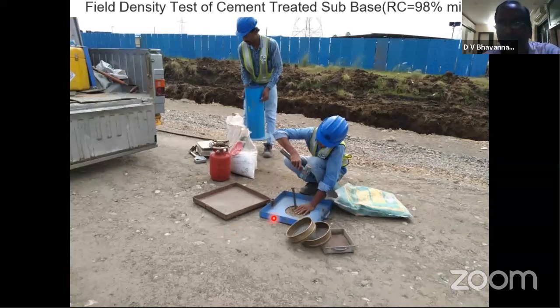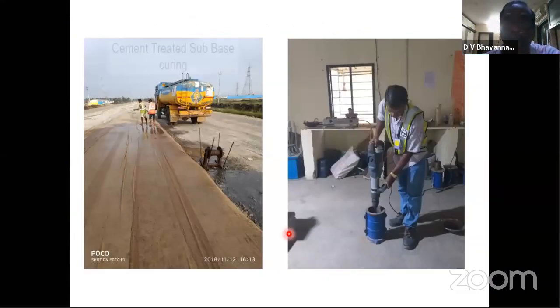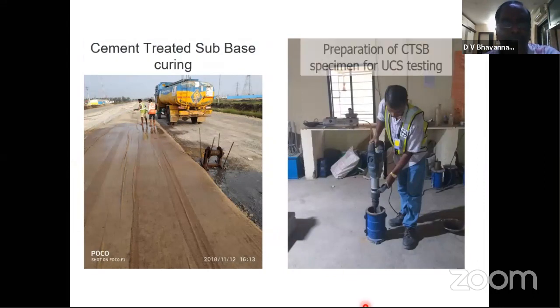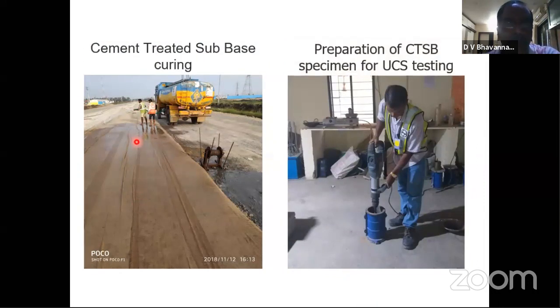Now the field density tests are conducted. We have to achieve 98% relative compaction for GSB. For GSB, subgrade, or wet mix macadam base also, we require relative compaction of 98%. They are conducting this test. Here, at the time of watering, CTSB looks like this. For 7 days we have to water it.